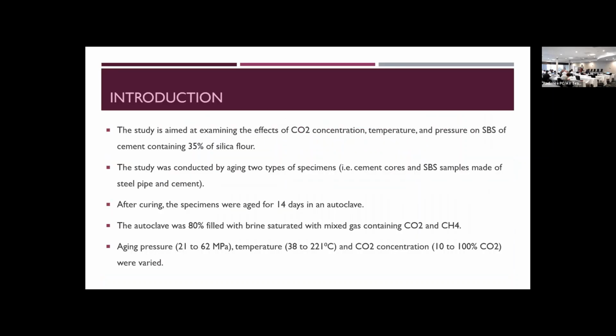What we have done in this test was to look at the same shear bonding, but from a totally different approach. And this approach was what happens if we have CO2. Particularly here, we were using a dedicated cement recipe, which was designed to have about 35% of silica flour. And that's why we believe that this presentation is very nicely linked to geothermal as well.